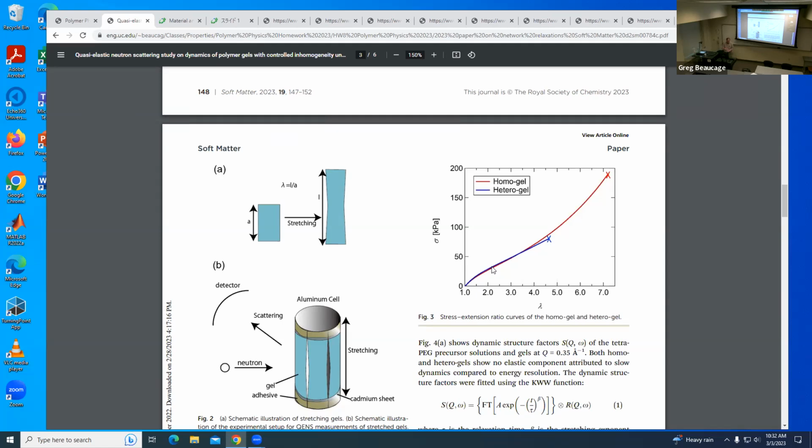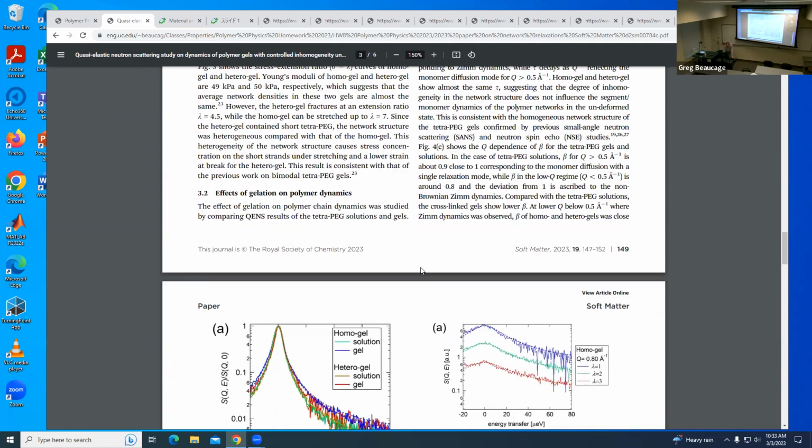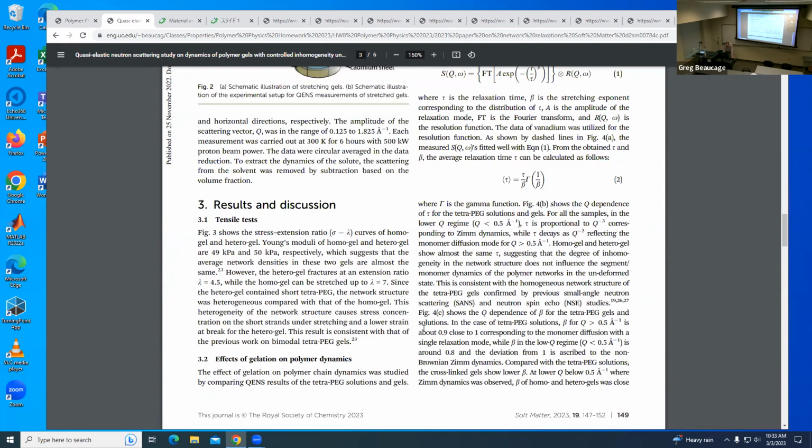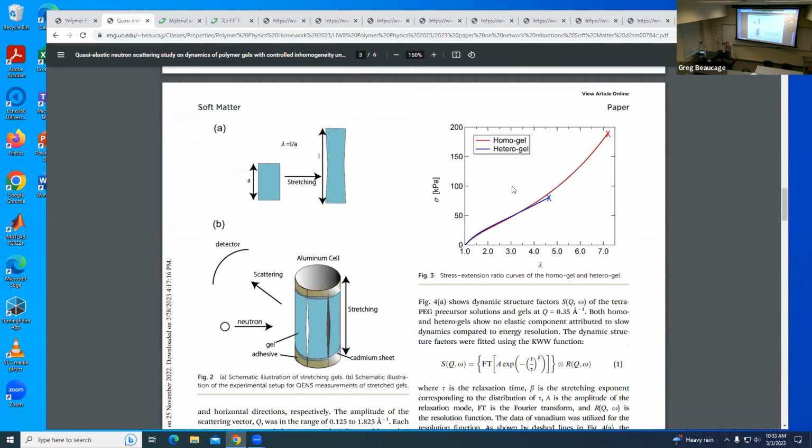So lambda is a strain. They have lambda 1, lambda 2, lambda 3. Lambda 1 times lambda 2 times lambda 3 equals 1, and it's fixed. It's incompressible. It's like a liquid. So liquid is incompressible, so this thing's incompressible. So when you pull on it, you don't get that kind of bond stretching, and even shows kind of what you get. You get some kind of rearrangement, right? In other words, it rearranges into something else. It can pull in from the sides. So you can see he's got lambda 1, lambda 2 are equal. When you have that situation, you don't get a linear part to this tensile curve. So you can't really do a tensile measurement on that kind of material.